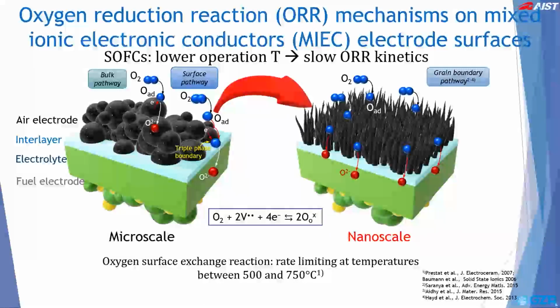This is important because at the nanoscale level, it has also been demonstrated by previous studies that the grain boundary pathway provides a much faster route that significantly boosts the oxygen reduction reaction kinetics. This indicates that a viable strategy to improve performance is through nanostructuring. By improving the oxygen reduction reaction kinetics, it may also be possible to lower the operation temperature without any significant reduction in performance.